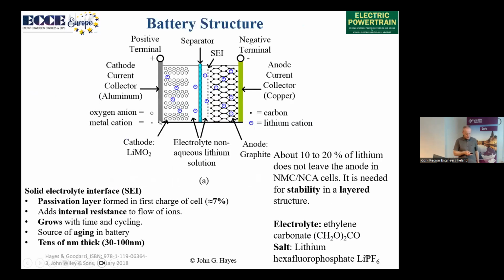So our battery structure is as follows. So we've talked about most everything here. So let's introduce a couple of new terms. In the very first charge of the cell, when we make the cell, we have this nickel manganese cobalt powder. We're going to mix that with lithium and mix it with a binder. So we're going to have all the lithium in the cathode initially.